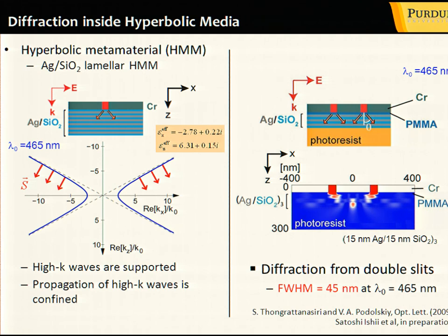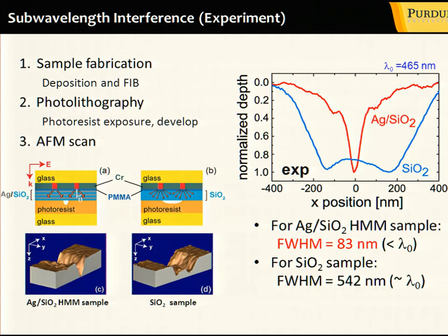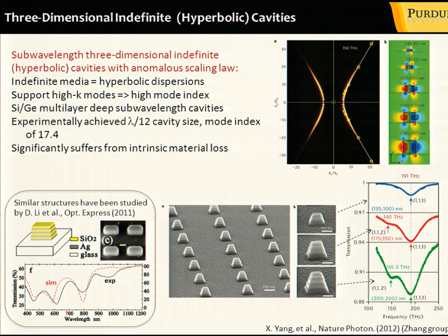If you have a hole here, then of course energy propagates perpendicular to this hyperbolic isofrequency surface. And if you have two holes, because of the interference, you would have a spot which could be much smaller than the wavelength because of this access to very large K, which could be much larger than omega over c. And indeed, that has been verified experimentally when you place the structure on top of the photoresist. We obtained a hot spot as a result of this interference between high-K modes propagating in hyperbolic metamaterials, which would be only 83 nanometers, which is 6 times smaller than the wavelength, and so clearly beats the diffraction limit.